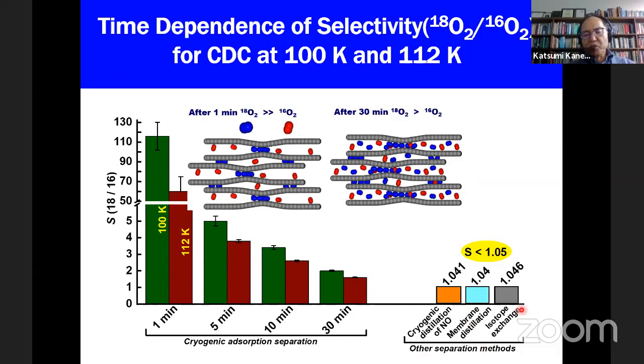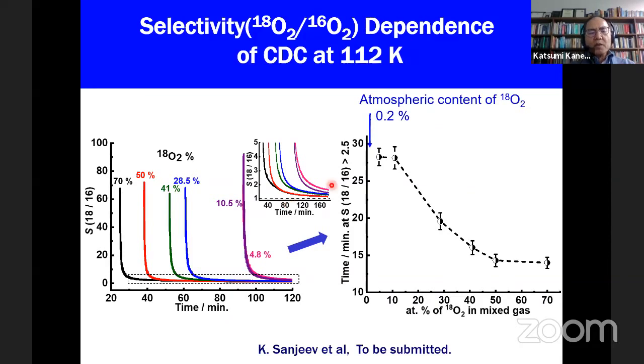Other methods, for example nitrogen monoxide distillation, membranes, or isotope exchange, give about 1.04, not really applicable, but this is very high. High selectivity is observed. Here I will also show you the composition dependence of the selectivity, at 70% or nearly 5%, and even at 5% a very high value at the initial stage is observed. So we assume 0.2% should probably be okay, but some improvements in the experimental system are necessary. At this moment we have just submitted our paper.